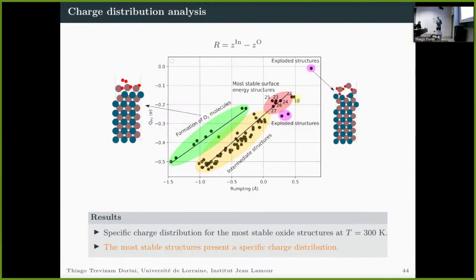And there are also the intermediate structures, which separate into 2 groups. It's interesting to see that the structures with the most stable surface free energy occupy a specific part of this graph. They are all located in this region, which leads us to believe that a real oxide that can form may have this charging configuration, in red, as you can see.